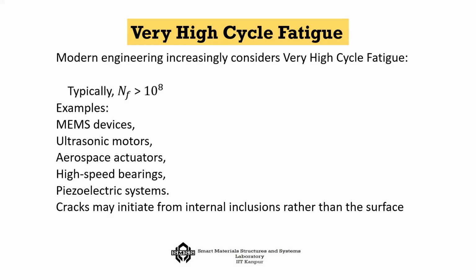Now, you can also have some systems in modern days which are very high cycle fatigue systems, that means N_f is greater than 10 to the power 8. Systems like MEMS devices, ultrasonic motors, aerospace actuators, high speed bearings, piezoelectric systems. In all such cases the failure can happen only in the very high cycle regime, and that happens because of the presence of internal inclusions in them. Generally they are very good for a long number of cycles, but ultimately when the failure occurs, it will be because of some inclusions that force the crack to propagate.